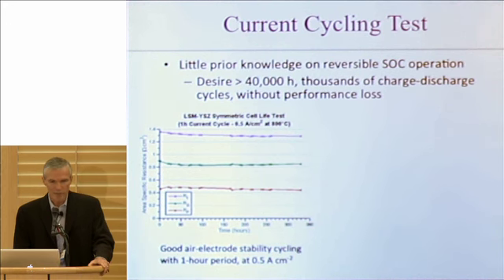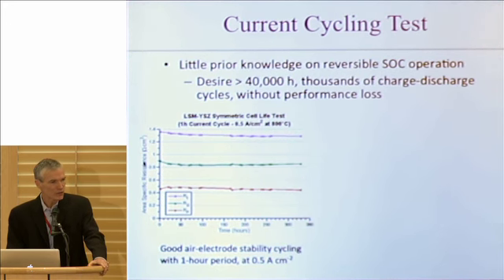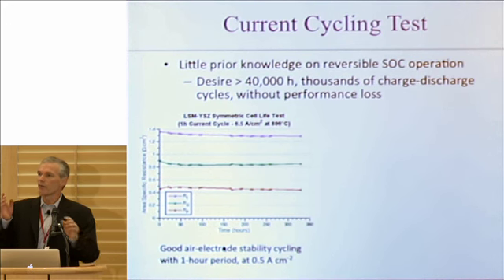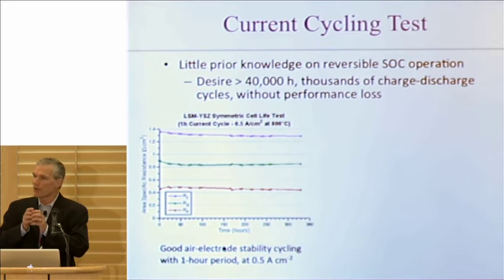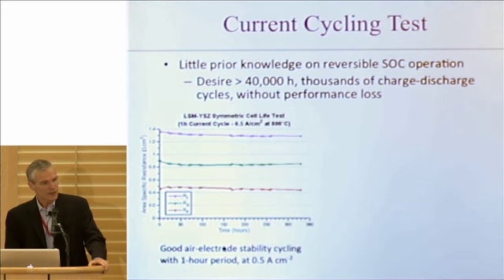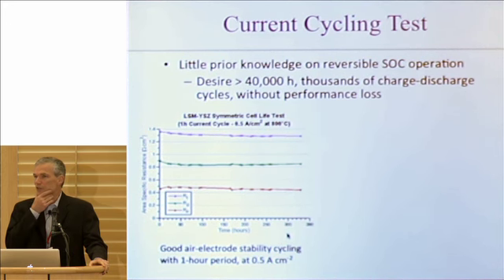Here's an illustration of some data, and I realize this is a little bit small. This is showing basically the resistance of the cell as a function of time. This is an experiment where every half hour we switch the current. So a half an hour we run the current, in this case at 0.5 amp per square centimeter in electrolysis mode. We turn it around and then do fuel cell mode for half an hour. So every hour basically we're cycling this thing. This test you can see was over about 350 hours, so we're at about 350 cycles of this device.